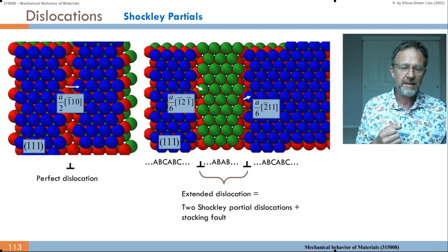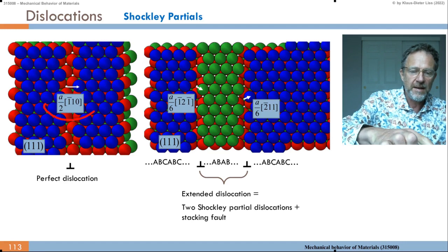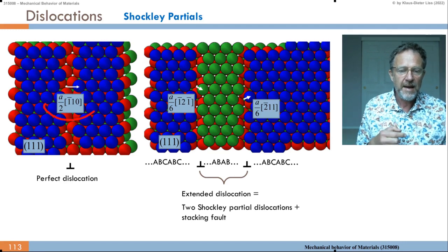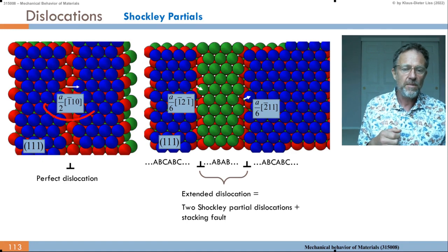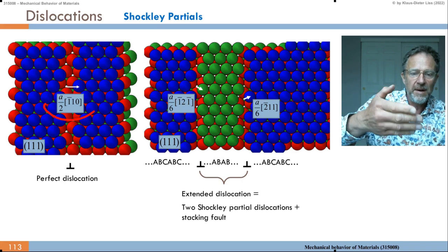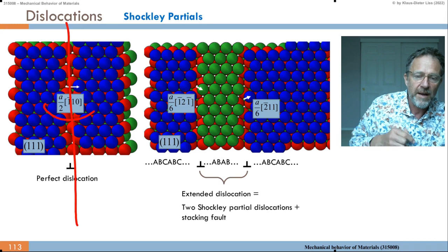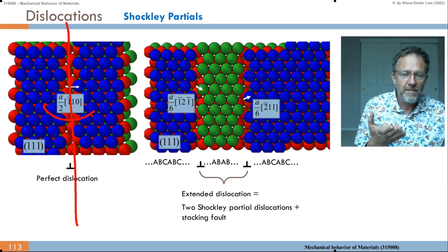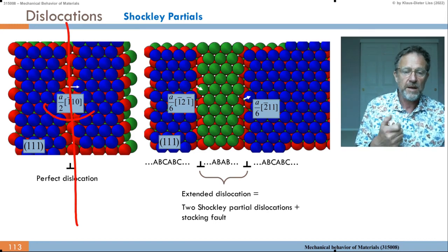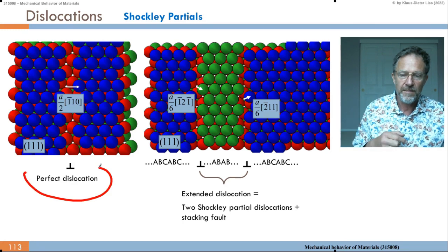Now, let's put a dislocation in. We know in the cubic lattice on the 111 habit plane, we have the Burgers vector as shown there, a/2 [-1 1 0]. That means putting one more plane in, as shown by the gap here. So above or below the drawing, we have roughly one layer of atoms more than in the blue layer. So this would be a perfect dislocation.